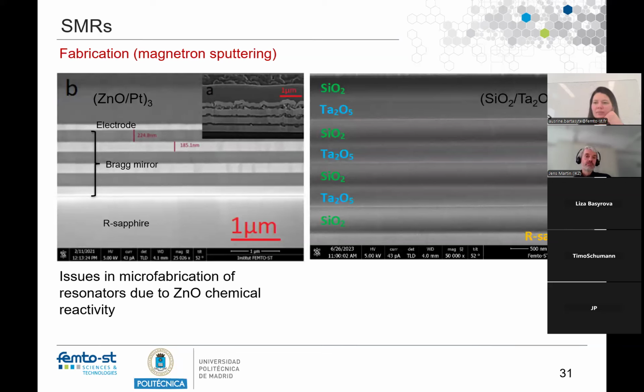In our lab, we are not very good at making membranes, so we decided to do SMRs and mirrors in collaboration with Marta's group in Madrid. We tried several types of mirrors, and in that center, we tried to grow zinc oxide platinum. Well, it's not a very good mirror, maybe from the price point of view. Then we had a problem with zinc oxide chemical instability, because when we did other steps for electrodes and so on, some parts etched out and we peeled off all the layers. So then we moved to Marta's mirrors on silicon dioxide and tantalum oxide.